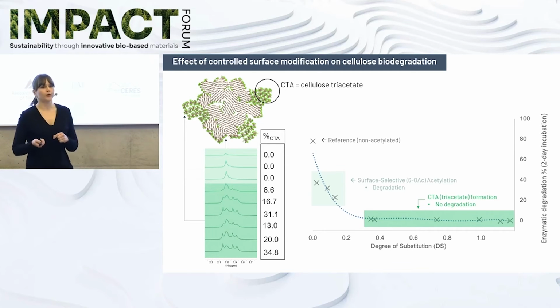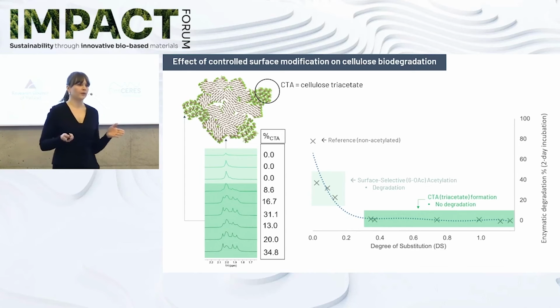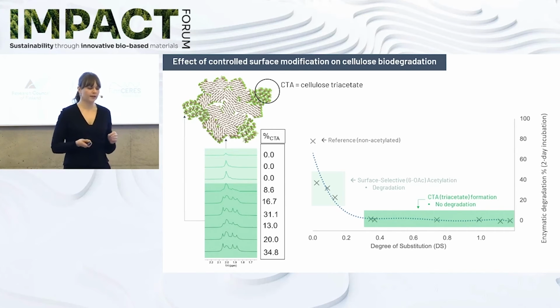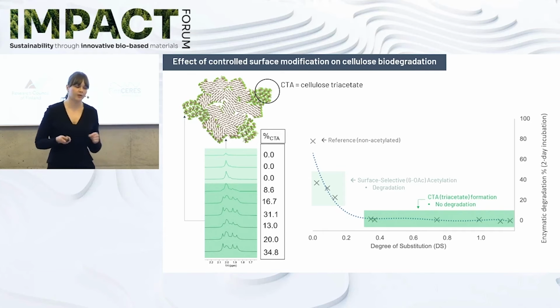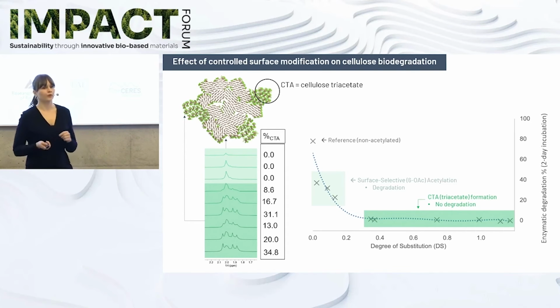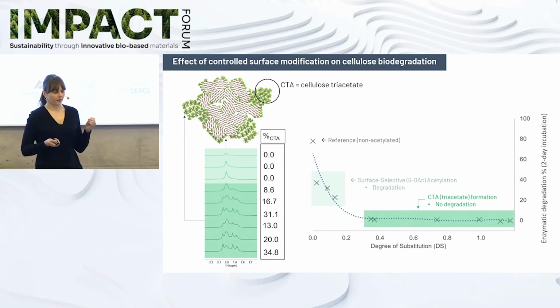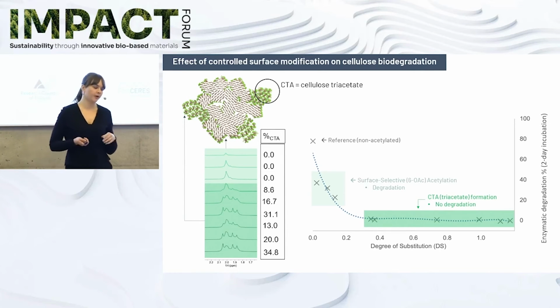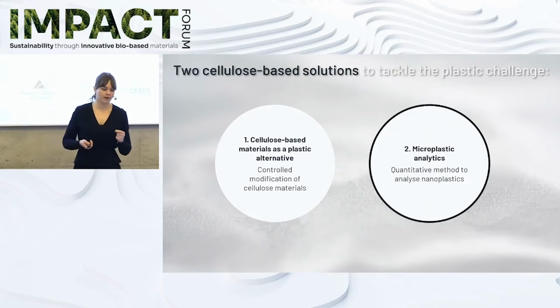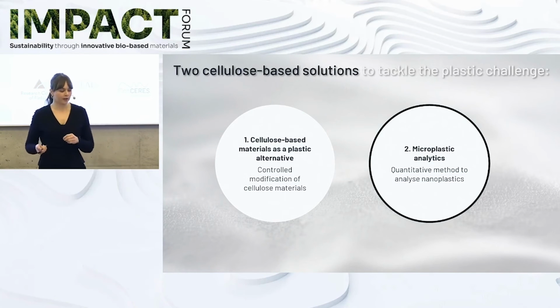But what is also important to note here is that even though this is from a natural origin, cellulose triacetate is very resistant to biodegradation and could actually also be a source of microplastics. So even though the other parts would degrade, it might be that these cellulose triacetate domains still remain and cause microplastics. And this brings me to the next part of the presentation, which is microplastic analytics. So we have used these surface-sensitive methods